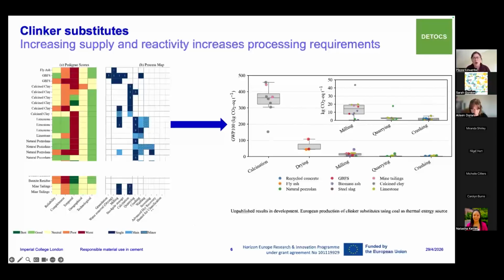So part of my work involves collecting data on how different clinker substitutes are produced. And we can then compare emissions from common processes that we use, like calcination, drying, grinding, and quarrying. Comparing data sets between materials also helps us build confidence and certainty in the result and helps us identify lower impact production routes for producing clinker substitutes. And we can use this data to then estimate emissions for new materials which might use the same processes. However, this level of analysis doesn't yet tell us how the materials will perform in cement.